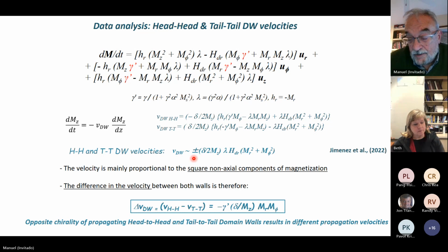The domain wall velocity is proportional to the thickness of the domain wall, and lambda is a parameter, and particularly it's important, it is proportional to the addition of the squares of the radial and circular components of magnetization. So we find that this difference in the head-to-head and tail-to-tail velocities can explain the difference when we apply the field in one direction or in the other. Well, I have to say also that to fit with quantitative values is not so easy, but at least qualitatively, we can understand this behavior.